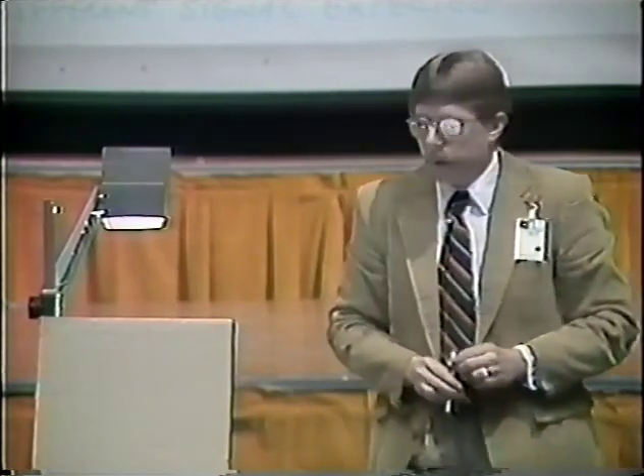Now, about the role of lithium. In the Fleischmann-Pons recipe, the 0.1 molar lithium deuteroxide solution, you have a 0.1 molar lithium ion concentration, a 0.1 molar deuteroxide ion concentration and a 10 to the minus 13 molar D+ concentration. So one question which a physicist like me can naively ask is, does the lithium plate out? You have a much higher cation concentration of lithium than deuterium. This is, of course, very naive.